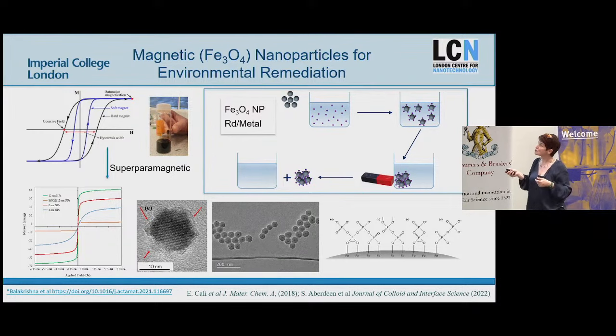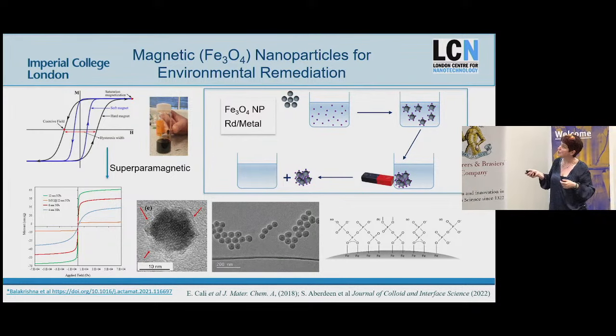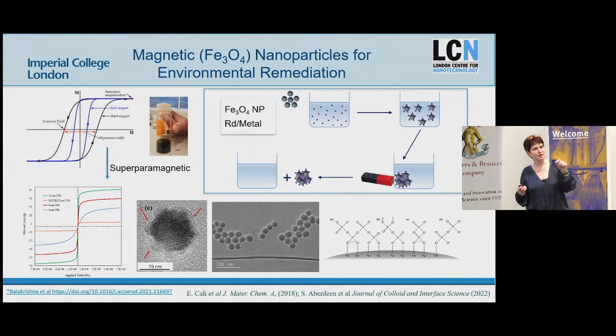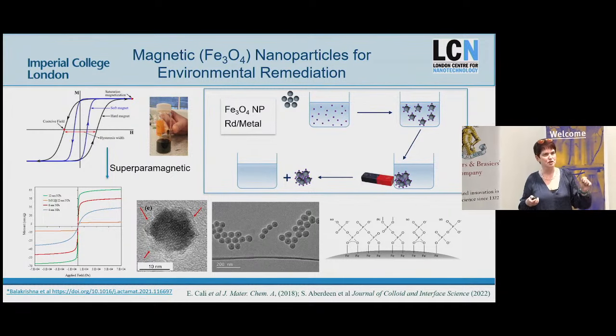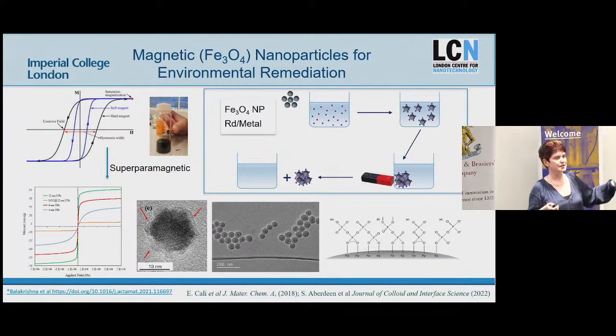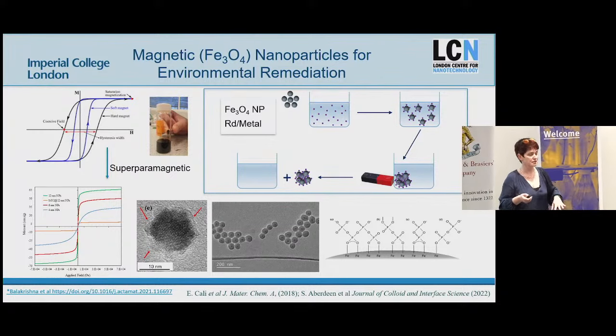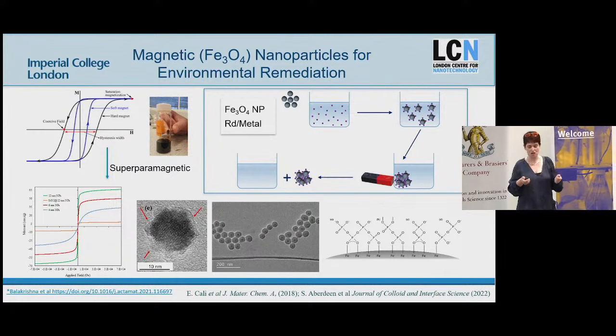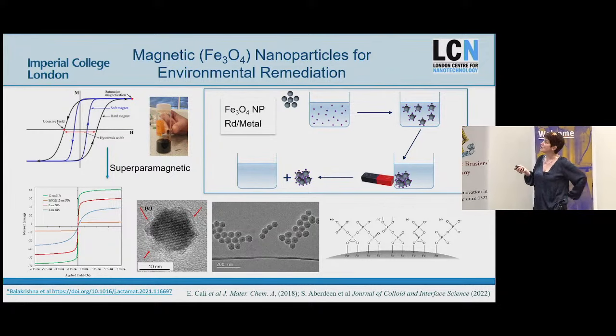And you get down to about 20 nanometers of particle size, and you end up in this superparamagnetic state, right? So you put a field on, it will magnetize, the spins will align. You remove the field, it collapses. So what you make with nanoparticles is effectively a magnetic switch, right? You put it in a field, it's magnetic, you take the field away, it demagnetizes. So being able to create a switch is critical to this process that we're going to look at.